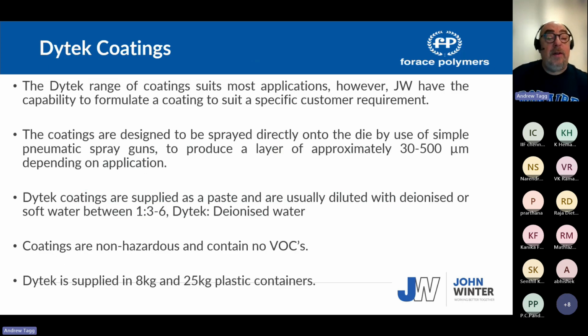So the range of die coatings suits most applications. They're designed to be sprayed directly onto the die using a simple pneumatic spray gun. The type of spray guns I prefer are the ones with the reservoir sat above, like they use when spraying cars. It's better with the reservoir above, because the person's hand will be manipulating the different angles, and it keeps a constant supply of coating to the gun. Most coatings are sprayed between 30 and 100 microns.